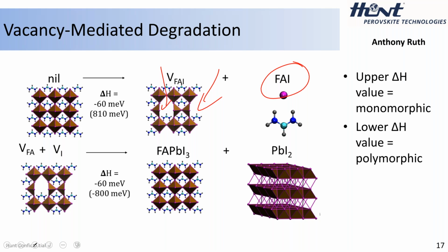I had shown previously that you can actually assist this process, since it's now endothermic, by the addition of water. It'll actually lower the energetics required to lose the FAI, but we're not going to show that today. Now, if you can form those vacancies, if you are able to have the extra energy to allow them to form, then this decomposition from FAPbI3 to lead iodide becomes highly exothermic, negative 800 meV. So in the polymorphic state.